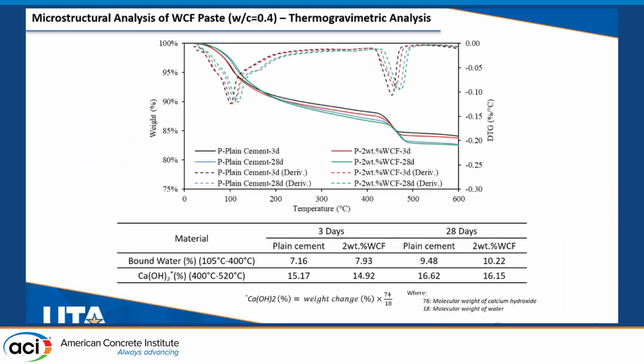Also, I used thermal gravimetric analysis to quantify the hydration products, namely bound water and calcium hydroxide. According to our results at different ages, the difference between these two products was less than 1%. That shows that incorporation of these fibers didn't change the quantity of hydration products. Now that we are confident that using these fibers, the hydration reactions and products are not affected, we can proceed with their evaluation on the macrostructural performance.